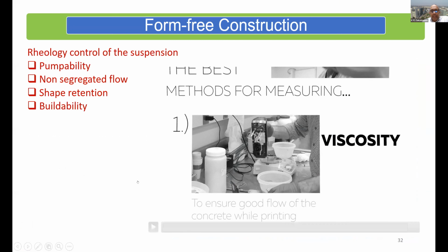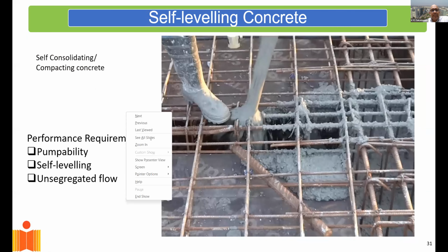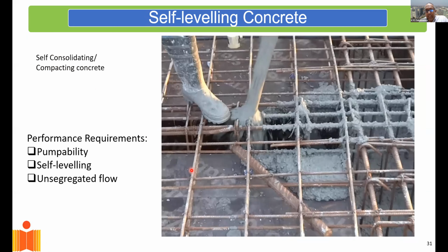So you see, this is concrete that is a self-compacting or self-consolidating concrete that, as you could see before, was able to fill the structure under its own weight. It flows under gravity, and it compacts by itself. It is able to fill the structure or all the gaps between the steel without the need for vibration. So this again was possible by engineering the mix to have this property of self-leveling ability.